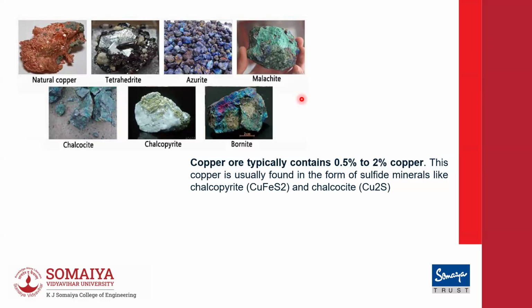And a steel plant basically processes roughly 50%, or let's say 40%, of unwanted material. This unwanted material is heated to 1500, 1600 degrees and processed. So you can assume how much energy is going there without any use. You cannot do anything about it. It is going to be there. The same thing, if you look at copper, is way, way, way worse, because a good copper ore typically has only 0.5 to 2% copper, which means, unlike something like steel, you're processing 98% unwanted material. Technically, you don't do it in the same way.